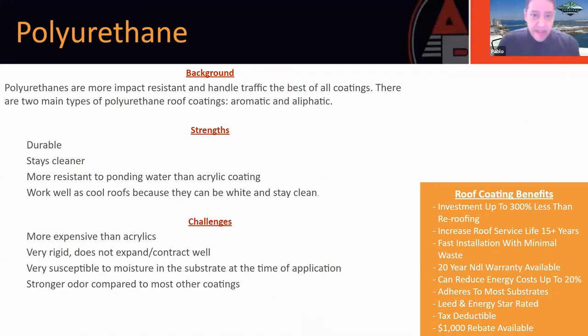Now, coming with that, the inverse of that durability is that it tends to be a little more rigid. So you don't have as much pliability with this type of coating as you do with the others, which tends to cause it to crack, especially in areas where there's movement in the roof. So that's a consideration when using this product.